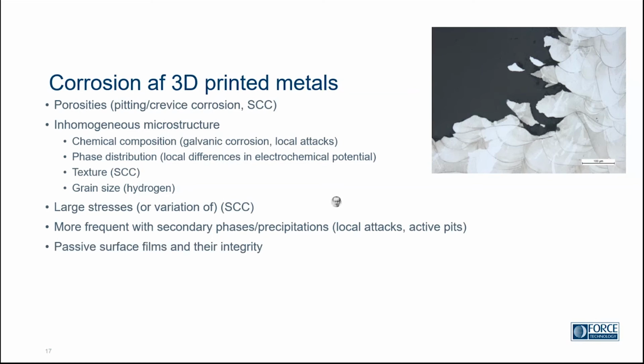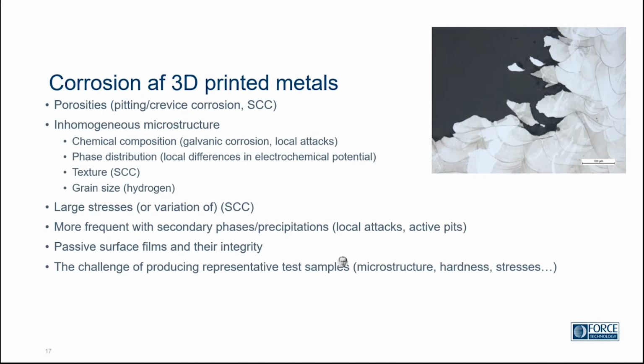And then finally, when you talk about stainless steels, for example, you have a passive surface film that protects the steel, and you also want to look at that quality, which is something you do with normal stainless steel as well. You also check that you have a sufficient surface film formed at the foundries. So essentially, when it comes to corrosion of 3D printed metals, the challenge is just to produce representative test samples, because we have this freedom of geometries, and so maybe some things affect the microstructure or impose different stresses.